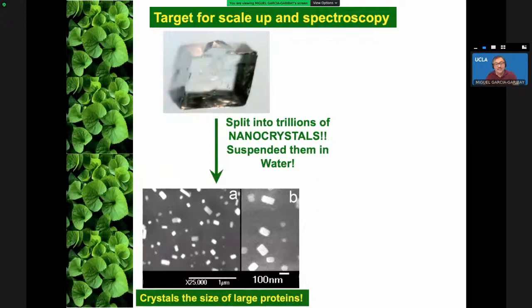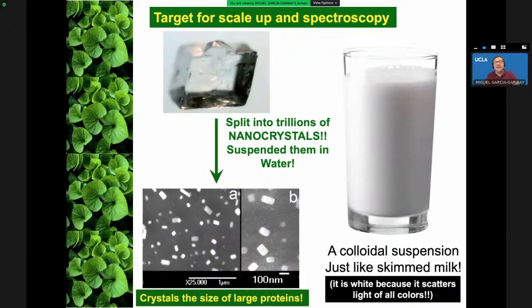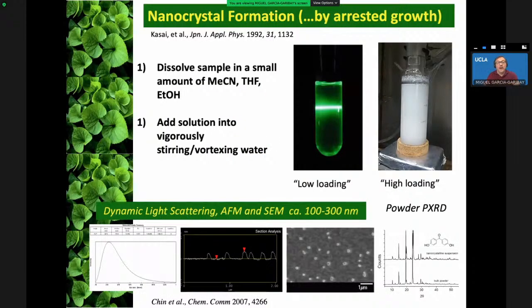The strategy is very simple, right? So instead of having a large macroscopic crystal, we went to split that into trillions of nanocrystals and suspend them in water. In this scanning electron microscopic image, you can see that the crystals are on the order of 50 to 100 nanometers, and that's perfect. Under those conditions, our crystals in water look like milk because they're a colloidal suspension. It looks like milk, of course, because white light is being scattered, right, of all colors, and that's what they look like. The way they are prepared is very simple.